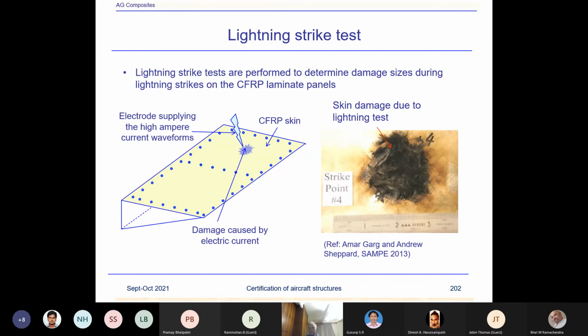And so what happens when you are trying to justify using this damage? Such a damage will be visible. If it's a very large damage, it becomes a visible damage, and the criteria of visible damage is followed for such damages. Suppose we are treating a 4-inch hole or 100 millimeter hole or 150 millimeter, we would try to determine the residual strength, whether it's limit load carrying capability or less than limit, and try to design the structure for tolerating this type of damage as visible damage criteria.